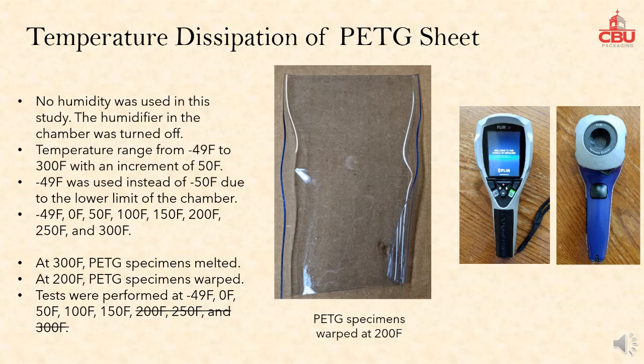A PETG sheet was conditioned for 24 hours with temperatures of -49, 50, 100, and 150 degrees Fahrenheit. The -49 degree instead of -50, because it was the lower limit the chamber could produce. The 150 degree was used as the maximum, because at 200 degree PETG warped and at 300 degree it melted.